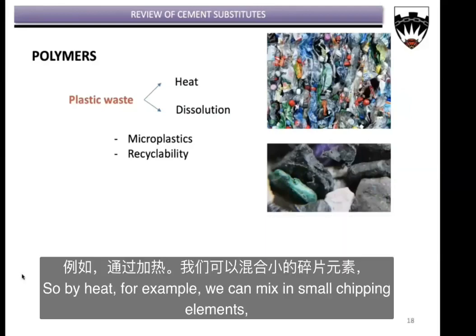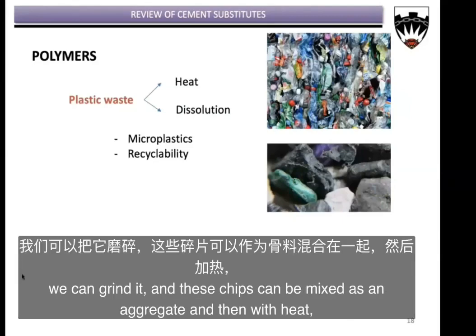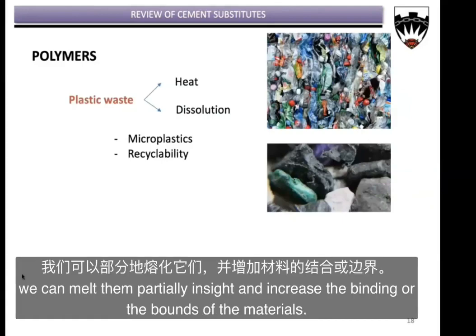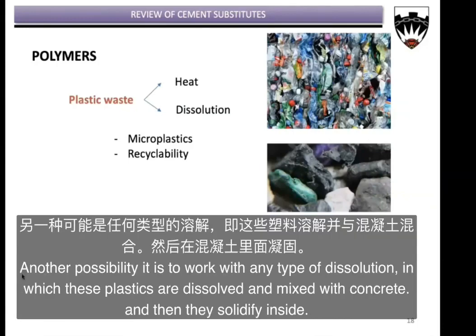So by heat, for example, we can mix in small chipping elements. We can grind it, and these chips can be mixed as an aggregate, and then with heat we can melt them partially inside and increase the binding or the bond of the materials. Another possibility is to work with any type of dissolution in which these plastics are diluted and mixed with the concrete mix, and then they solidify inside.